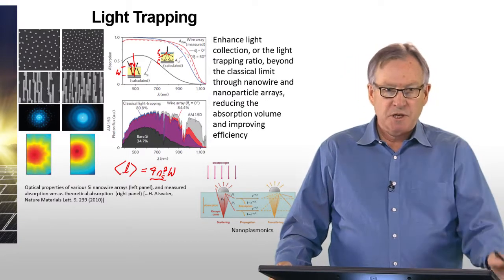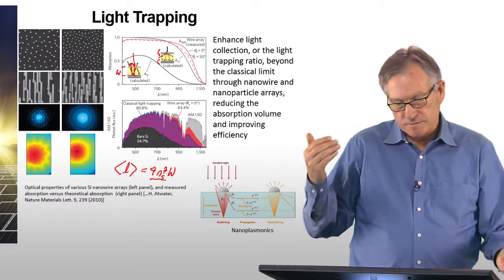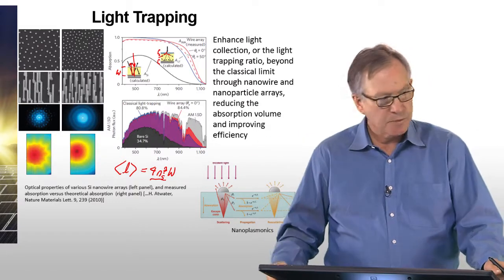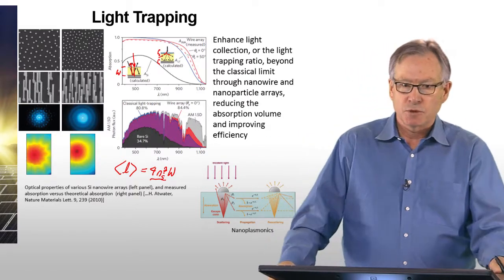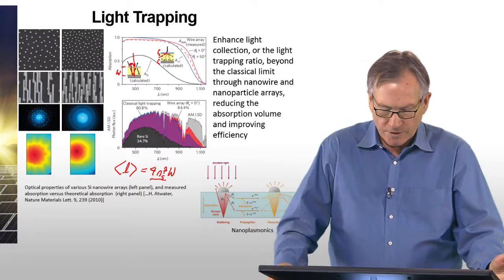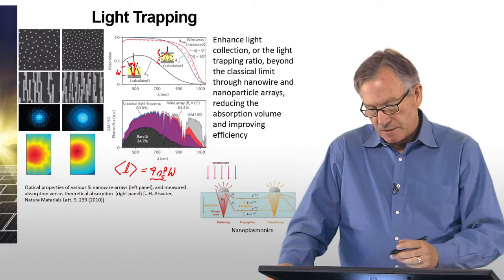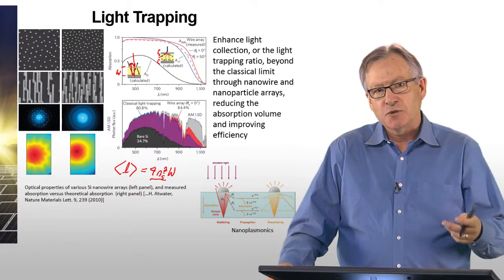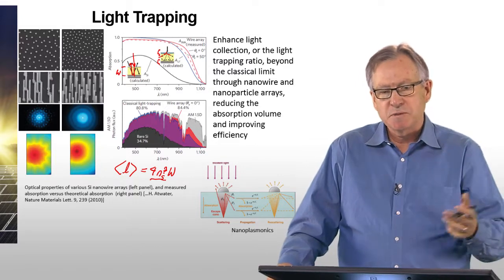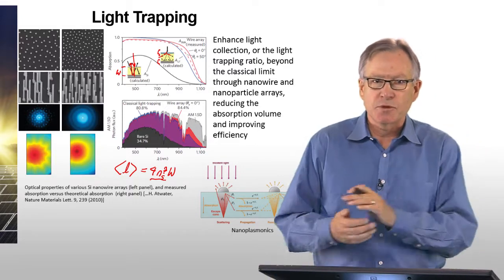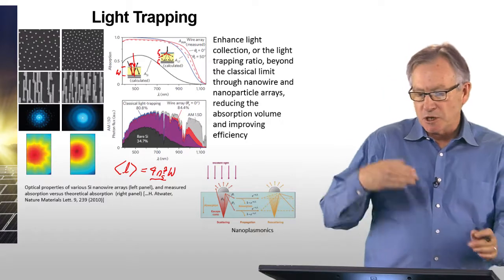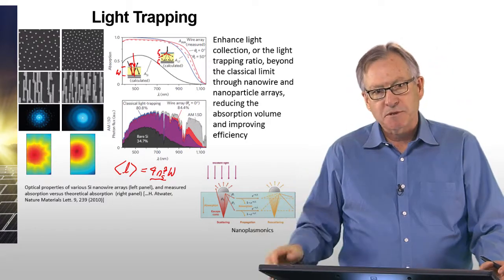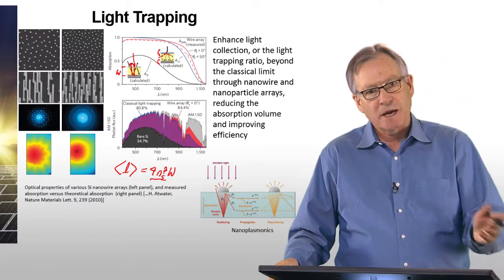And n for a semiconductor can be on the order of 3 to 4, so therefore the enhancement can be quite large. It can be over a factor of 50. Okay, but can you go beyond that? One of the things being looked at using nanotechnology is whether you can go beyond the classical light trapping limit, this 4n squared limit, and actually have a longer path length.